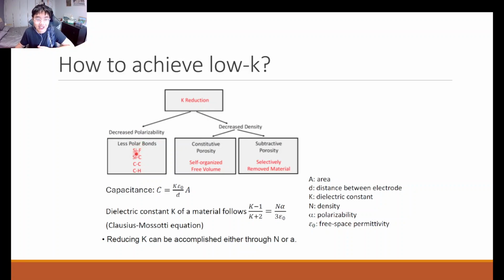However, there's a slight incorrect labeling in this diagram, because you may say that your silicon-fluorine bond is quite polar, right? Because your fluorine is a pretty electronegative element. However, you realize that the silicon-fluorine bond is not so polarizable due to the small electron cloud of your fluorine atom. So even though it has a large dipole moment, it does not have very high polarizability as well. So these are certain bonds that we can use in our dielectric material to replace your silicon-oxygen bonds, for example, in your SiO2.